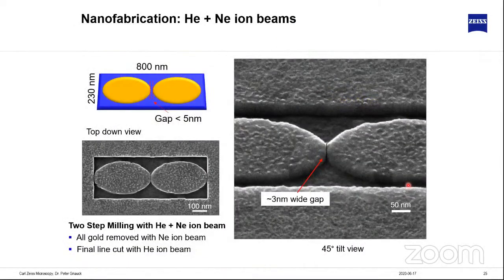And I'd like to show you a few more examples. This is a high resolution example. Again, this is a nanoresonator. What we wanted to have is two round shapes with a gap in the center, which should be smaller than 5 nanometers. The whole sample is basically gold on glass. What we did is we used the neon beam to do some rough milling around it, and then we used the helium beam to make the fine cut here. And if we measure the size, we have a cut which is in the range of 3 nanometers. And I think there's no other technique in the world available that can really do these extremely fine structures.